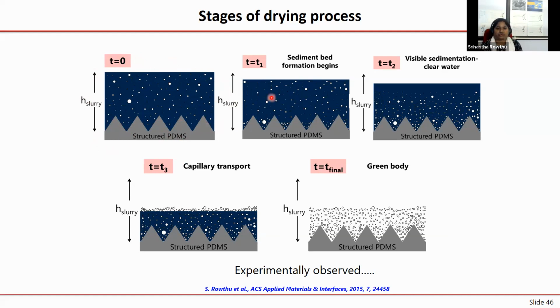However, as you are letting it dry, simply because this liquid is evaporating from the top, and your PDMS also has intrinsic porosity, that means this water, if there is any audience who understands the wetting part, PDMS is a hydrophobic material, which means if I put liquid water on it, the liquid water is not going to spread on it.